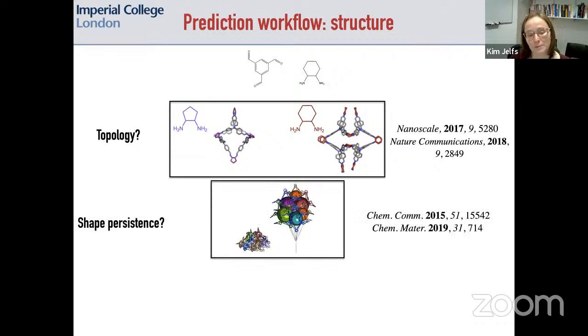And that relates to this next point of what you want to be able to predict, which is shape persistence. Shape persistence I'm using here is the feature whereby even in the absence of solvent, the molecule maintains a permanent cavity. So it's porous. As you get with the balloons on the right-hand side, it's porous and open rather than the collapsed structures that you get on the left side that we say lack shape persistence. And shape persistence typically in these systems, where we've actually done large screens of thousands of them, is a really rare feature, that maybe about 95% of the systems lack shape persistence. So you're looking for the rarer needles in the haystack of the shape persistent systems.